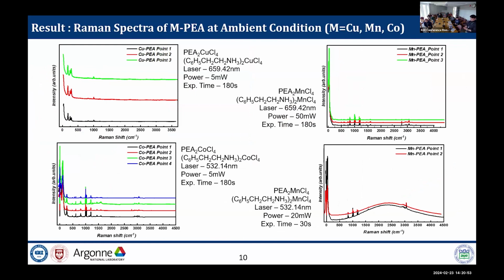This is the result here. We first measured the Raman spectroscopy of the ambient sample. We can measure different samples and find the optimal condition to measure them. In this Raman signal, we can see that the organic molecule signal over 400 inverse centimeters is almost the same, same as the phenethylamine hydrochloride. But under 400 inverse centimeters, this part is the lattice mode, so every sample is different. So we are using DFT or other methods to figure out every different vibration mode. This is work in progress in Korea and at Oak Ridge National Laboratory in the USA.